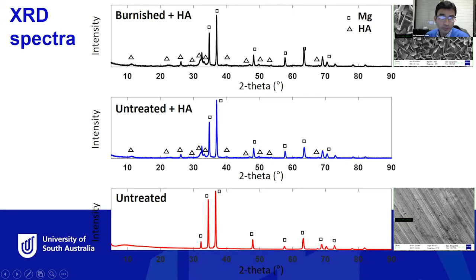We can see that especially around the diffraction angle of 27 degrees to 30 degrees, you can see the formation of the HA crystal peaks on the surface from the XRD. And we can see that the peaks are a little bit higher in the case of the burnished plus HA coating as compared to the untreated plus HA coating.